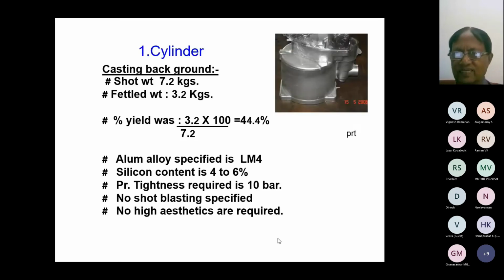Cylinder, this is the casting background. This is one casting. The shot weight was 7.2 kgs, and the fettled weight was about 3.2 kgs, and percentage yield was only 44.4%. Aluminum alloy specified is LM4, and the silicon content, as you know, is 4 to 6%. This is a hypoeutectic alloy. Pressure tightness is a mandatory 10 bar, it has to withstand. No shot blasting is specified. No high aesthetics are required. This is an under chassis casting.